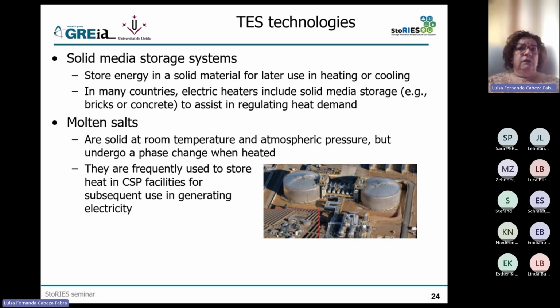But other salts are being considered, both to improve the energy efficiency, but mostly to increase the temperature of this storage, because the higher the temperature of the storage, the higher the temperature of the steam produced, and the better efficiency in the turbine side. And here there are a lot of challenges. When you go to higher temperatures, maybe nitrate-based salts are not good enough. We have to go to carbonates, chlorides, and this brings a lot of problems. Not only, but one of the biggest problems is corrosion. But I say not only, because also stability, it's a problem.